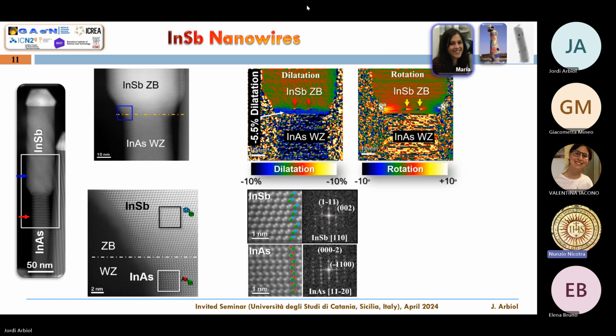So here there are many mechanisms. Indium arsenide is an hexagonal structure. You can see a kind of zigzag of the atomic layers. These are the 001 layers that are having this zigzag structure, AB, AB, AB. And then this is the cubic structure of the indium antimonide, which is an ABC, ABC, ABC piling of the atoms. So the stacking is quite different in one and the other. But what you can see here is that all the strain is released at the first 5 nanometers of the nanowire, and then everything grows relaxed.